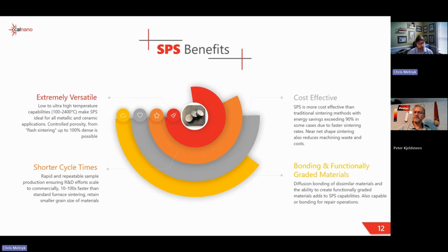No, I think it's on the power delivery side of things. We don't have one of those units, so I can't speak too much about it. But it's just a desire on how you do that, and same with the pulse conditions. There's on-off DC, square wave, sinusoidal pulses. So even just in the delivery of DC, there's a few options that sometimes have no effect, sometimes have significant effects. You can run it in burst mode or cut it, things like that. In a quasi version of the FAST system, you can do a capacitive discharge, just build it up, and not quite to the same extreme level, but you can flash sinter as well.